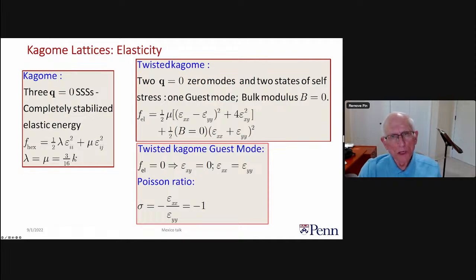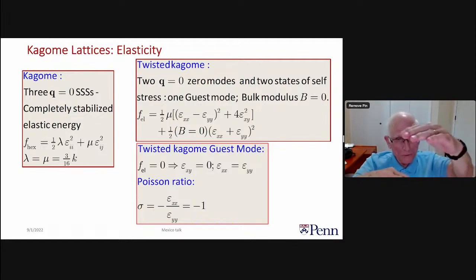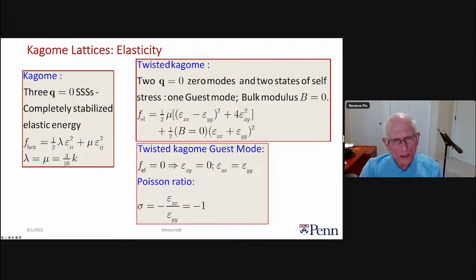So you can see that this would say that the Poisson ratio, which is the ratio of the compression to the stretch, if you take a rod and you pull on it, stretch it out, normally you expect the rod to compress in the direction perpendicular to the pull, but the twisted Kagome lattice has the opposite behavior. When you pull on it, it increases in size.